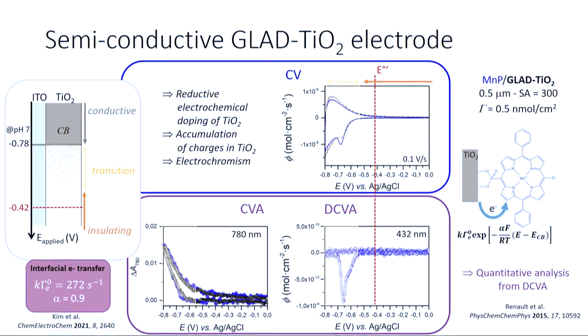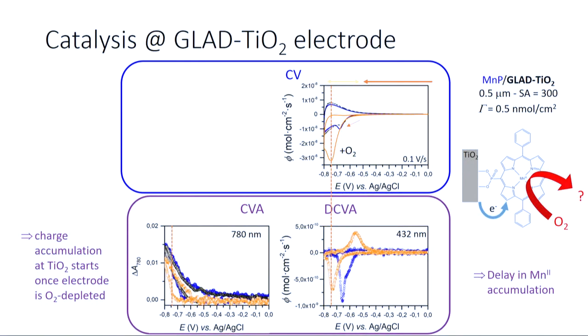So under these conditions, we spent a lot of time to develop models and investigate this kind of interfacial electron transfer, and we developed a model for quantitative analysis of this electron transfer from this derivative cyclic voltabsorptogram, and we could extract the parameters of this irreversible interfacial electron transfer. Okay, so the next point is what's happening now if we add the catalytic process in this semiconductive titanium dioxide, just like we did for indium tin oxide.